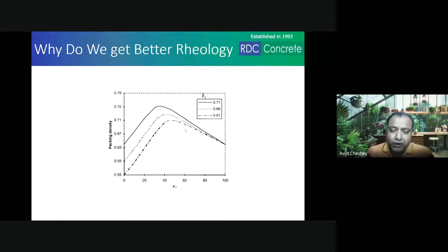And what he did was a study with natural aggregates again. So beta 1 is the particle packing, the void content or the packing density of each aggregate. Now it could be the same size of aggregate, 20 and 20 on both sides. You are having 20 of both same size aggregates, but sorry, beta 1 is the particle packing of the aggregate which is smaller in size, or the other, as compared to the standard one.